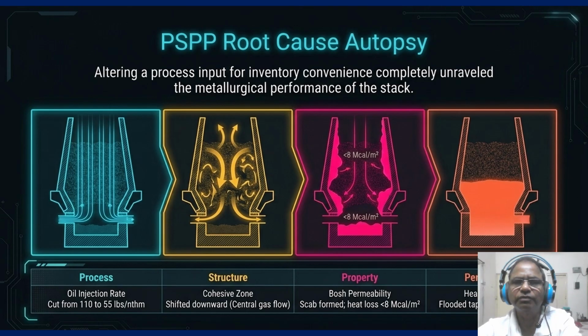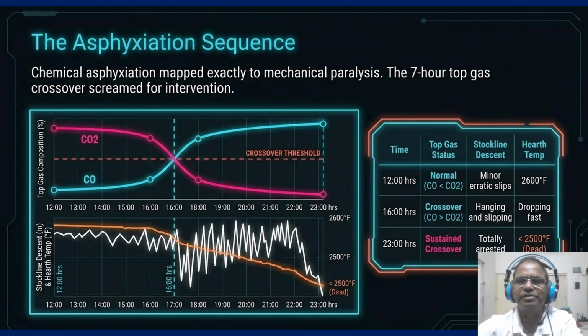The final result of this broken chain was a chemical problem that we could see in the gas data. So, coming to the sequence of the events, as the slide shows, is a smoking gun. So look at the top graph. The neon pink line is CO2 and the electric blue line is CO. At 1600 hours they cross. This is the crossover threshold. When CO exceeds CO2, the furnace is no longer reducing.